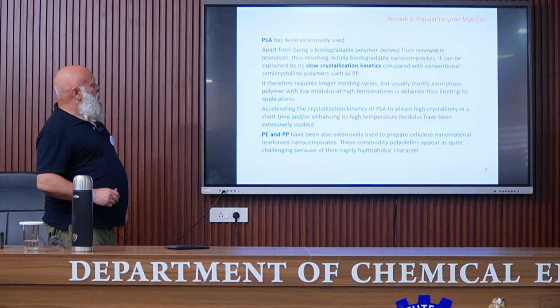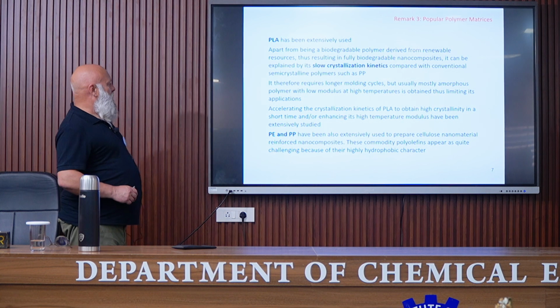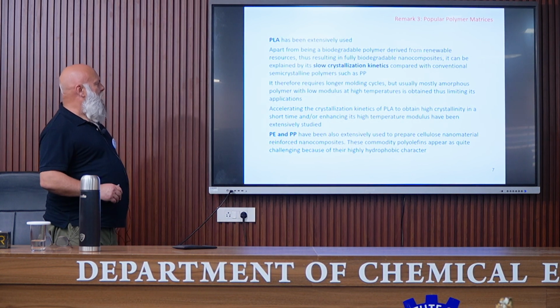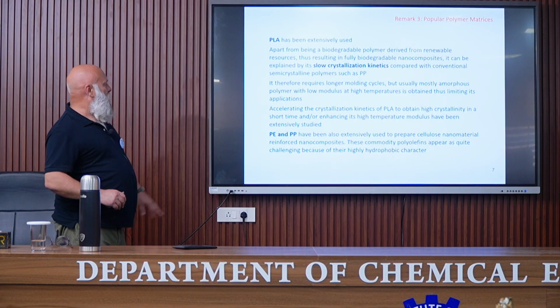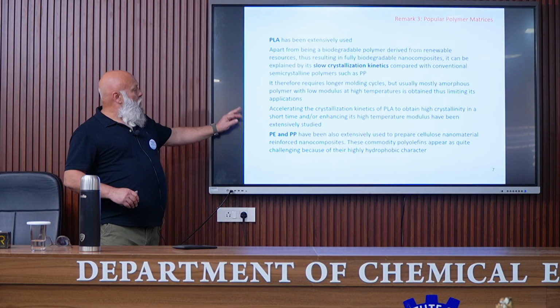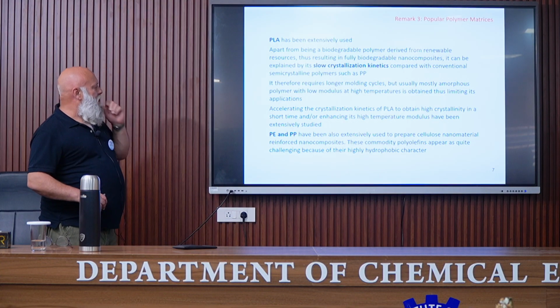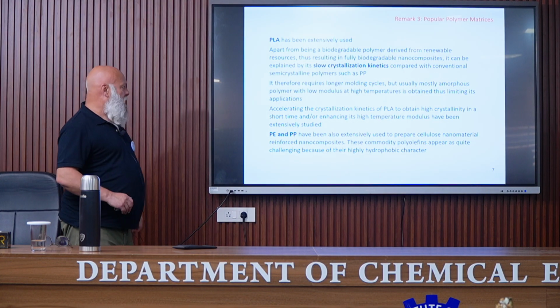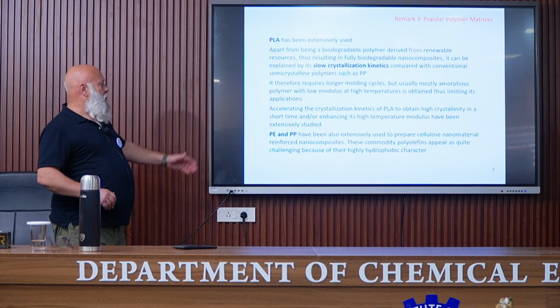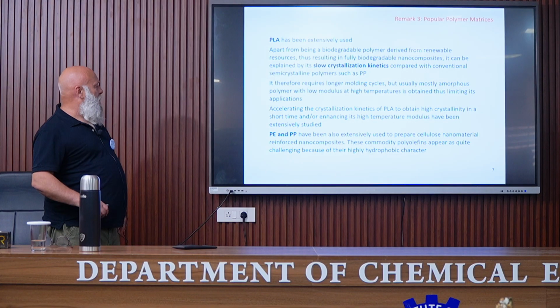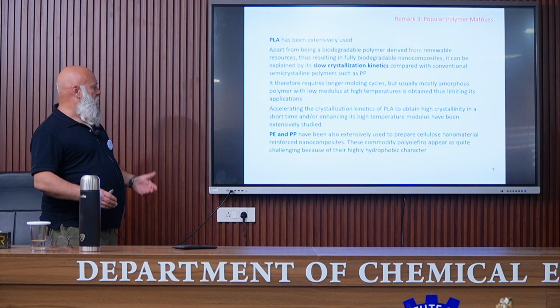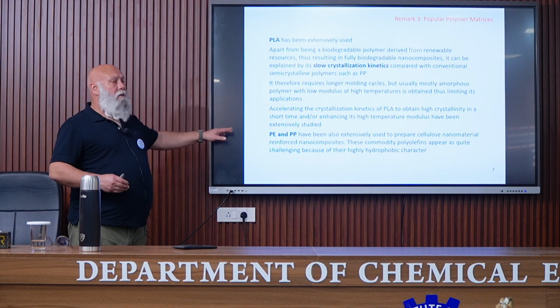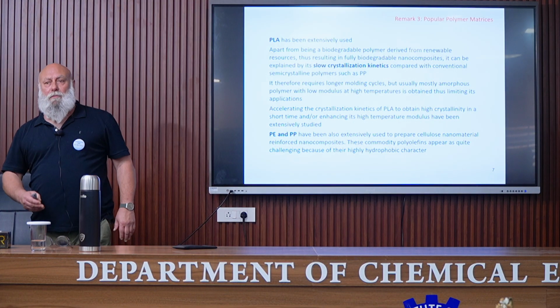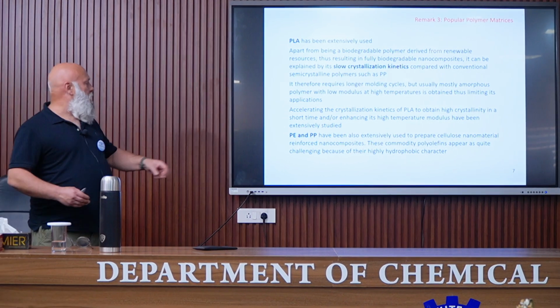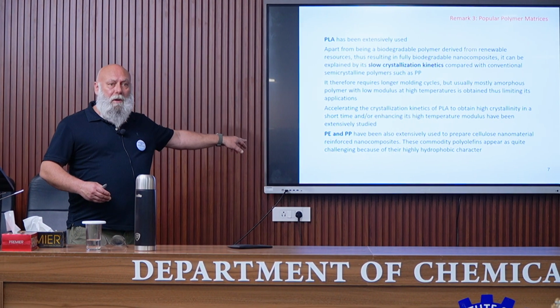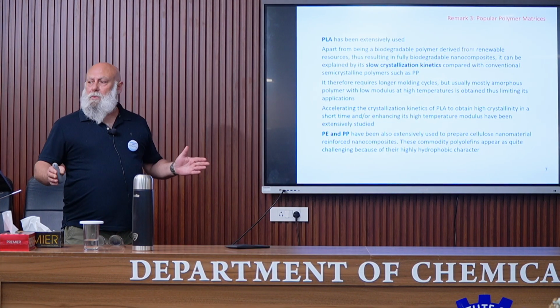Accelerating the kinetics of crystallization of PLA to obtain high crystallinity in a short time, enhancing its high temperature modulus, has been extensively studied. You will see in my slides that mainly I use polyethylene and polypropylene. They have been broadly used. The reason is that, of course, these polymers are considered commodity polymers. They are broadly used. And the other thing is that these polymers are highly hydrophobic. So it means that if you succeed in dispersing nanoparticles in this polymer, it can work with any polymer.